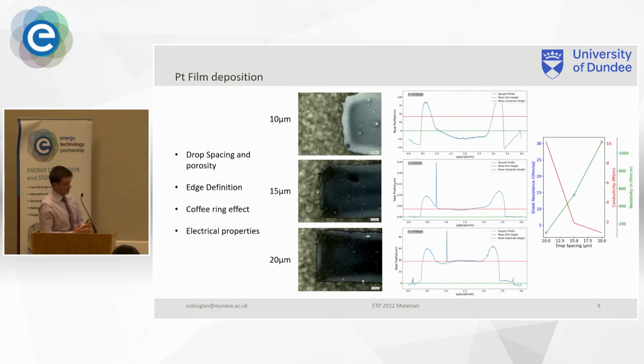So from there, I've then taken that ink and I'm printing some deposits, and this is just a simple test of printing a 10 millimeter by 2 millimeter strip of line and changing the drop spacing. The drop spacing is the distance between each droplet. As we print so many droplets in a line, we can define the distance between each droplet. Turns out defining this distance can control the porosity of the deposit, and as I increase the drop spacing, the porosity increases, and we can see how this affects the edge definition of the deposit, the size of the coffee rings that we get,